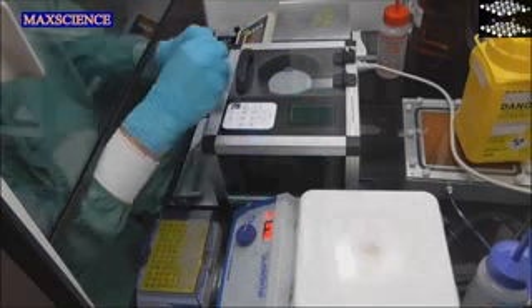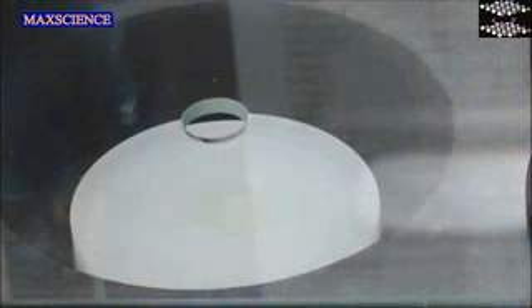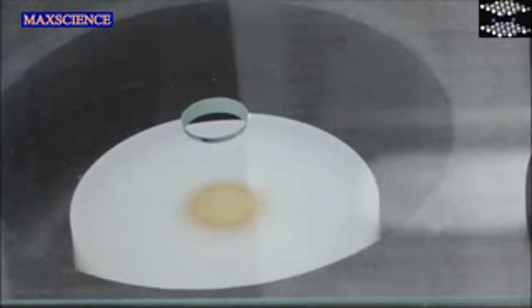Transfer the PEDOT:PSS coated substrate from the hot plate and place it onto the spin coater and spin it at 3000 RPM. Now dispense 30 microliters of the ink onto the substrate and continue spinning for 30 seconds. This will produce a bright yellow film. Place the substrate back onto the hot plate held at 90 degrees Celsius.